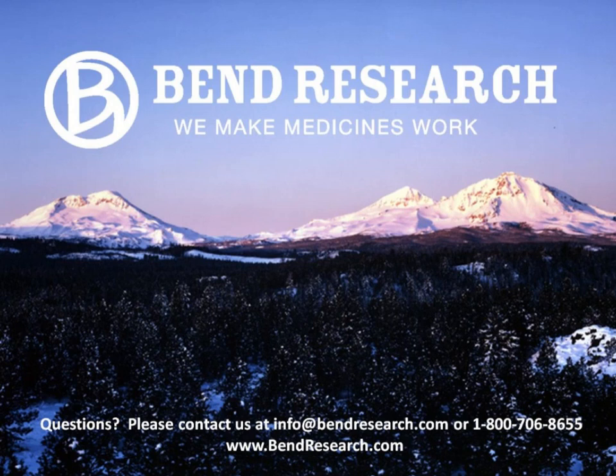That said, there are a number of technologies, or I would say adjuncts to the technology, where we have looked at suspending crystalline drug in a non-solvent that the polymer is soluble in. And what that allows us is to spray dry effectively encapsulated drug crystals in a polymer matrix.